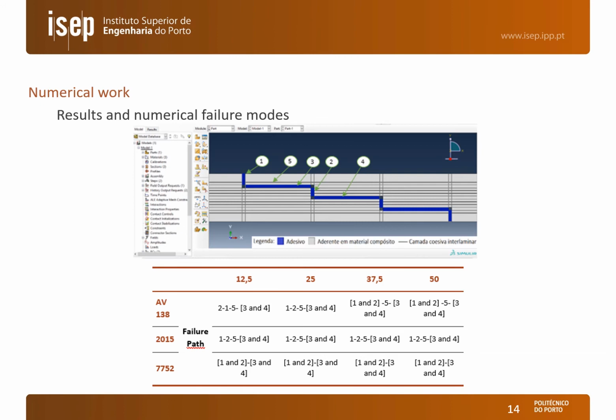And then we can see that we have a more or less consistent behavior for all conditions, in which first we have failure of the butt portions 1 and 2, and then we have failure of the steps denoted by the numbers 3 and 4. The main difference here was the absence or not of interlaminar failure.